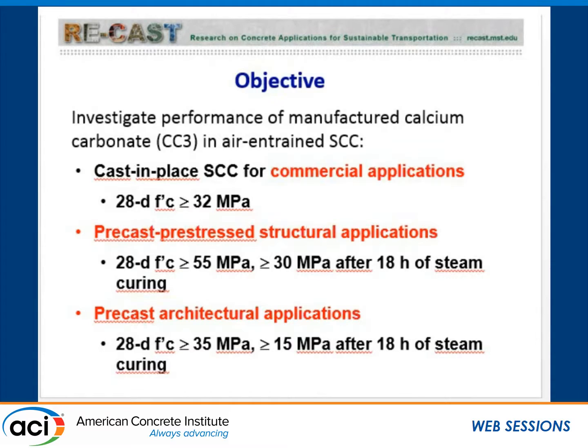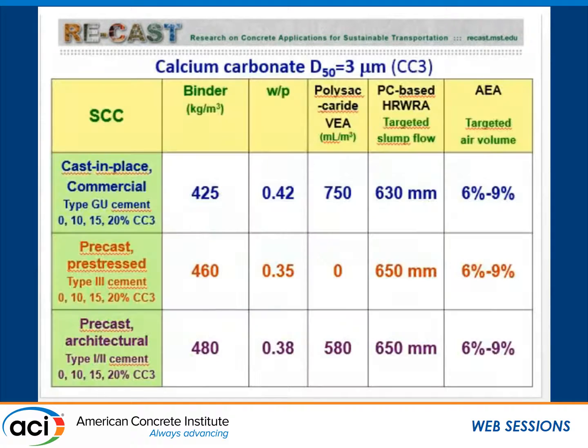is precast architectural applications. So the requirements on the strengths are not as high. They are 35 MPa, 5,000 PSI at 28 days. And the requirement after 18 hours of steam curing is not 30 MPa, it's 15 MPa. Or if you would, it would be 20 MPa after 24 hours. And I'm sorry for the metric units, but this is American Concrete Institute, so get used to it. So the calcium carbonate that was used, like I said, the D50 was the 3 micron, and these are mixture proportioning.